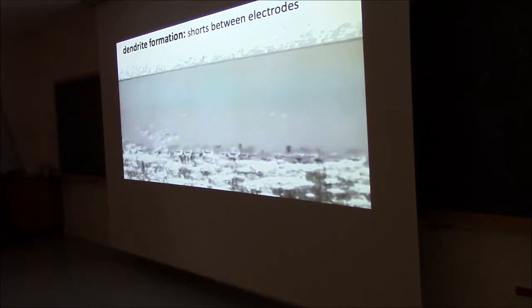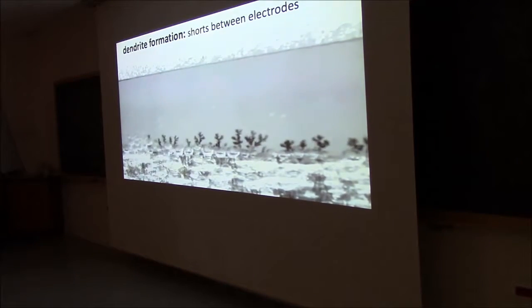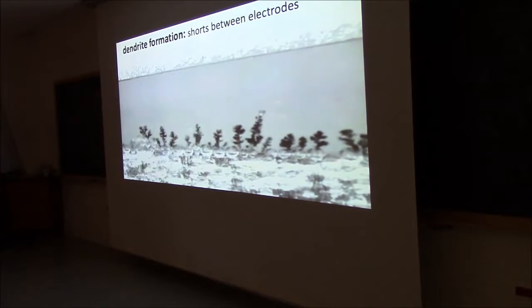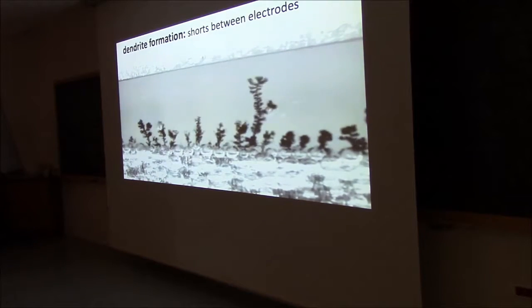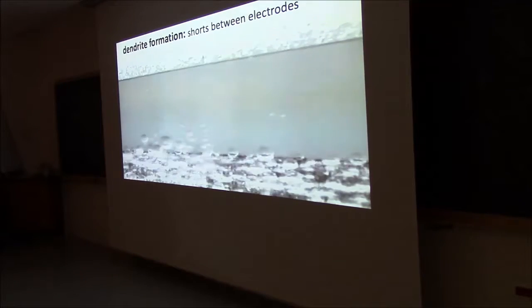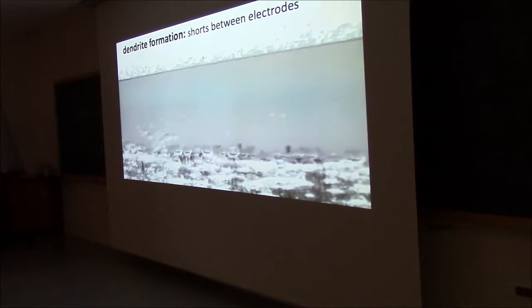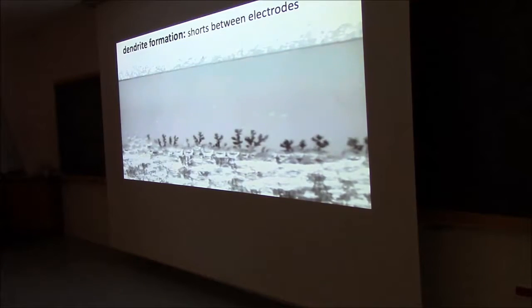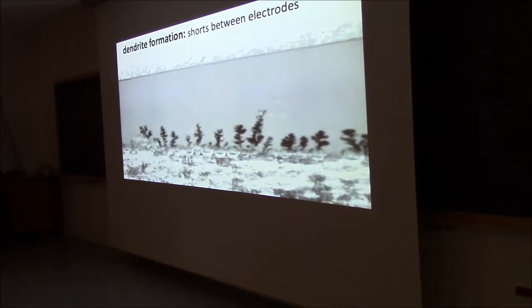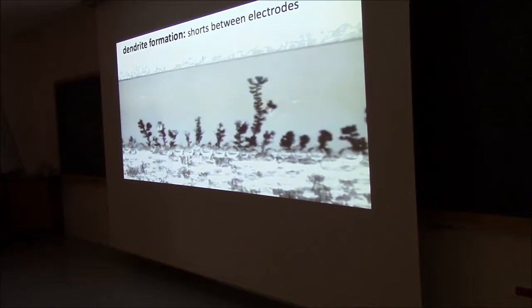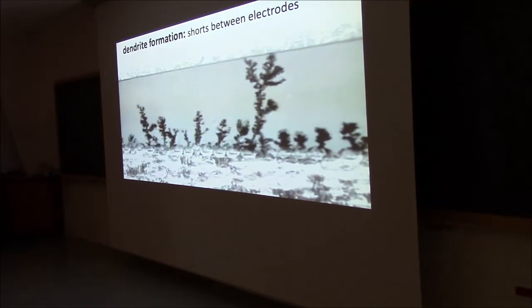And this is happening because if you have a little bit of the lithium pointing out, the field lines are focusing to this point. So all the new lithium is really focusing to this point. That's why it's growing out. It's not going into the rest of the structure. People are looking into putting a coating in between, which is thin, so the lithium is able to pass, but you have an influence on the field lines, if you can limit this. So this is very much happening if you deal with pure lithium metal as an anode. As long as people cannot get rid of this, there's no point in going in this direction. This effect is much less in graphite.